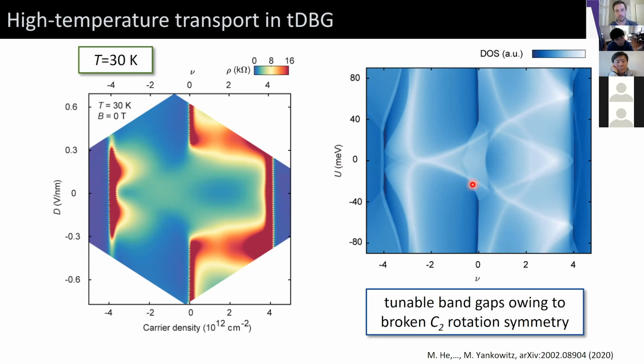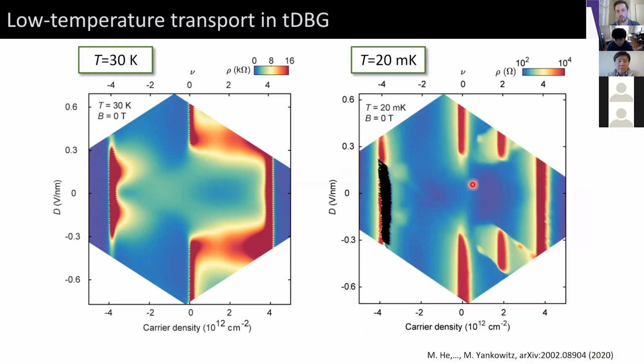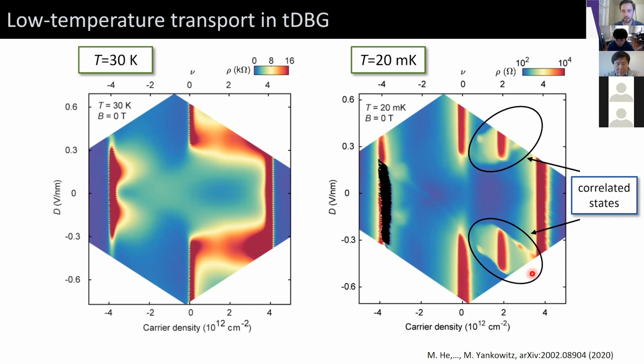So now we want to cool the system down to 20 millikelvin and see what of that survives and what new might emerge. Okay, so the salient features here are actually quite similar to what we see at high temperature, including these gaps in neutrality, the gaps at full filling, and now a sharper version of this cross-like feature. But in addition, we see new features which are not explained by the single particle model. So those are these insulating states now that emerge strongly at half filling of the conduction band, more weakly at quarter and 3/4 filling, and then also this halo-like region marked by a weak increase in the device resistivity. And this is a pretty sharp boundary between the inside of the halo and the outside at low temperature.